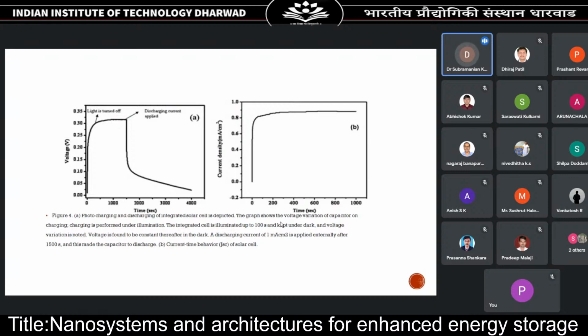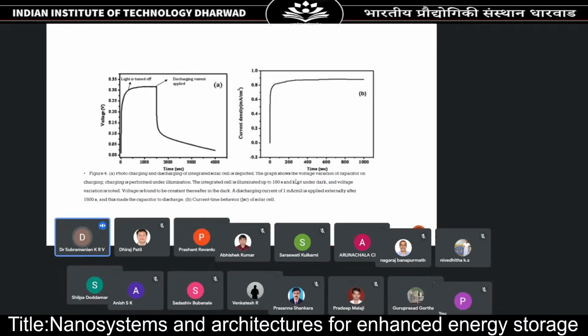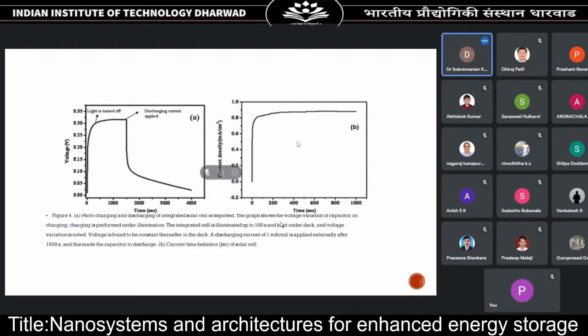That means whatever solar energy is shone on the DSSC, the charges have been stored in the dye, and they are responsible for the open circuit voltage. Only when you apply a discharging current at about 1500 seconds is the discharge triggered. You can see that the discharge goes on up to 4000 seconds. Figure B shows the current time behavior of the solar cell. As the light shines, the current increases and then reaches a saturation value. This is the proof of concept that you can simultaneously shine solar light as well as charge in the same structure.